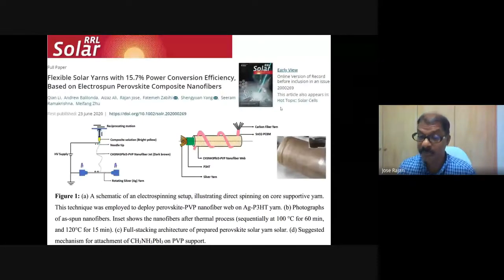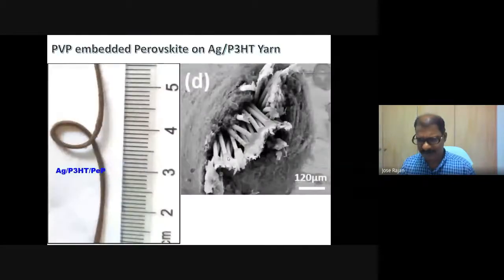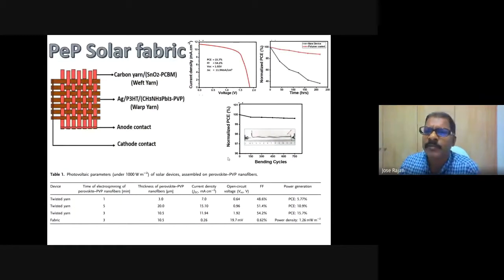a polymeric medium. Let me skip ahead, I think I'm running out of time. When we do this, you can see the black curve is the uncoated device, and uncoated means not dispersed in polymer. You will see that the power conversion efficiency rapidly drops to 0. But that's not the case when the perovskite is included in a polymeric matrix. It is pretty stable, and we could develop this fiber into large scale. What you see here is a perovskite fiber bundle created using this methodology.